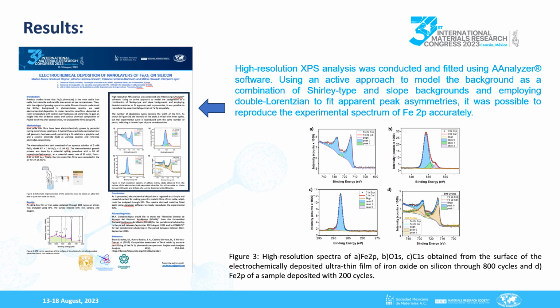Peak fitting was used to determine peak center and widths. A combination of Shirley, Sloping, and slope background were considered for background. The main iron peak had a double Lorentzian form. Its characteristic spin orbit splitting and binding energy position, along with the fact that only one oxygen peak is bonded to it, demonstrate the presence of iron-3 oxide as the only phase in the film.